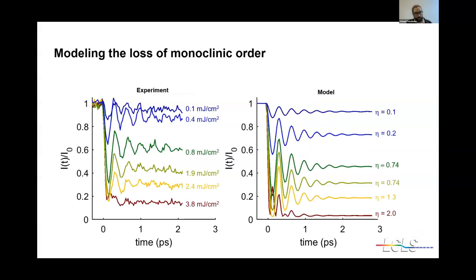Then we took this sample to LCLS, and at LCLS, you can pump the same monoclinic peak. And what you'll see is that the monoclinic peak is suppressed, and as I'll show later, it doesn't recover for a long time. But we can model that suppression of the monoclinic order, because now a drop to 0 perfectly corresponds to a complete melting of the charge order.